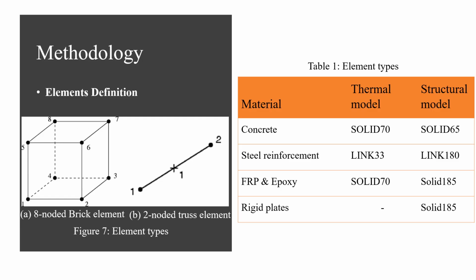Now, as we know, finite element modeling involves finding analysis results at all nodes of the elements that form the whole structure. Therefore, each material was defined using a suitable element formulation. For instance, in the thermal model, concrete was modeled using element Solid 70, which is an 8-noded linear brick element that is capable of transferring heat via conduction, convection, and radiation.